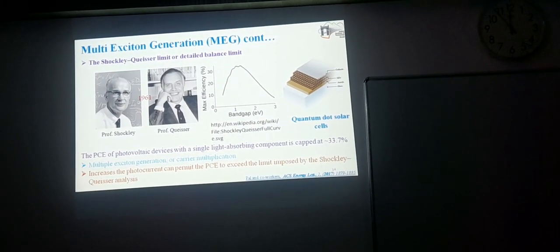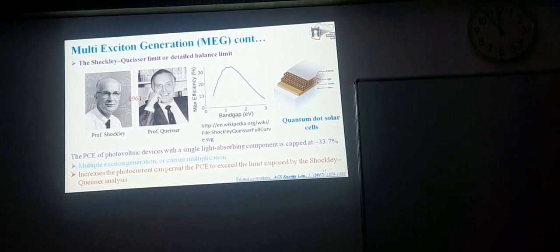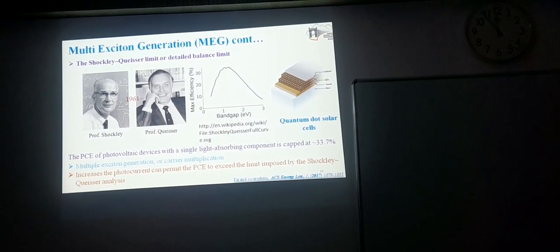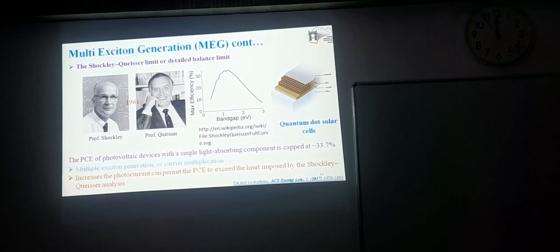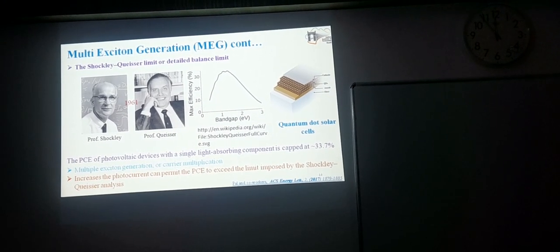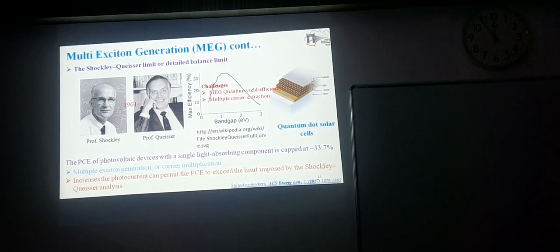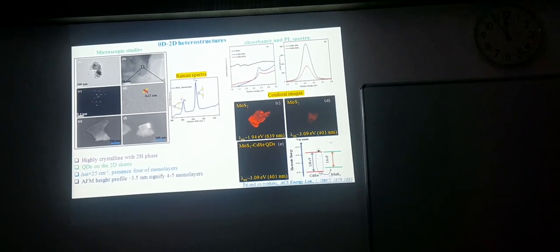So this is possible only when you have quantum dots. Quantum dots fall in the quantum regime. We call this a quantum material, right? It has discrete energy levels in the conduction band as well as the valence band. So if you can excite this material with twice the energy of the band gap, you can generate more than two excitons in this system. But you need a specific site to dissociate the charge carrier and also for collection. So we were very lucky to do this work, generating multiple excitons in this quantum system with a 2-dimensional material. Here we use 2D molybdenum disulfide as a site to accept the charge carriers generated by multiple excitons, and we were able to show this fundamental physics, how much time it takes for this charge carrier generation as well as the extraction of the multiple excitons, and we showed that it is possible to exceed the 33.7% power conversion efficiency limit in the system.